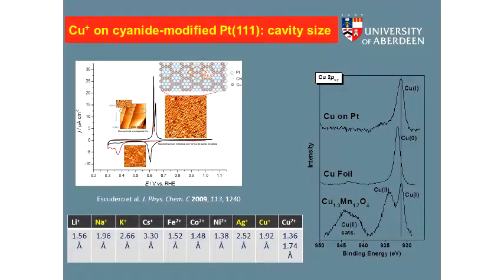But there is something more interesting yet with this. Well, obviously here, when I talked before about using many cations, if you are working with lithium, sodium, potassium, and cesium, you are not going to reduce them in aqueous solutions, never, because you have to go so negative that before you start reducing the ions, you will start evolving hydrogen.